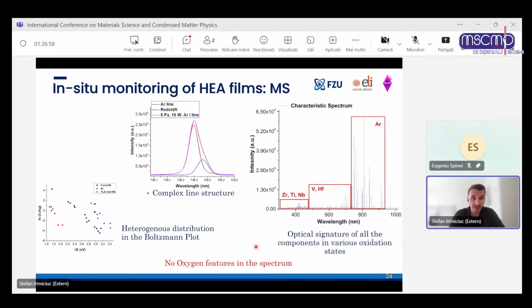And when we looked at the magnetron sputtering plasma, we saw three important features only by looking at the optical emission spectroscopy of the plasma. So we saw that there's a really nice distribution between elements as a function of the wavelength. We also saw that when we do the Boltzmann plot, we don't see any equilibrium, but what we see is that argon and some elements sort of group together, so we will have partial equilibrium for specific elements.